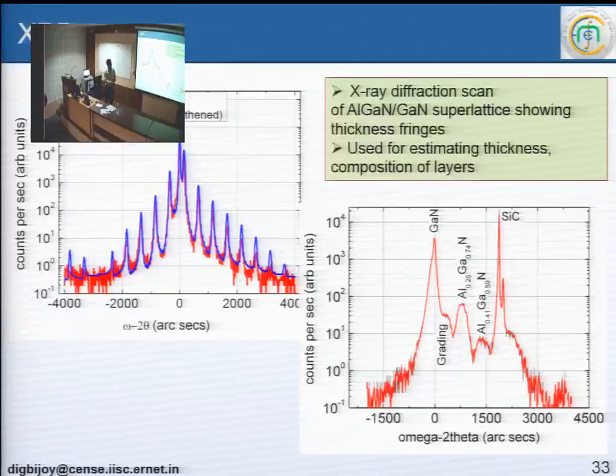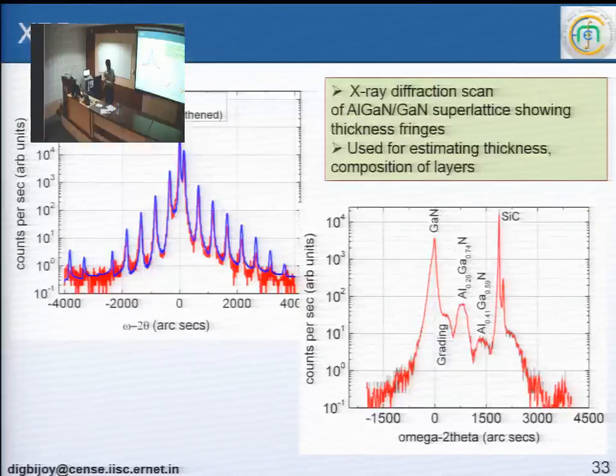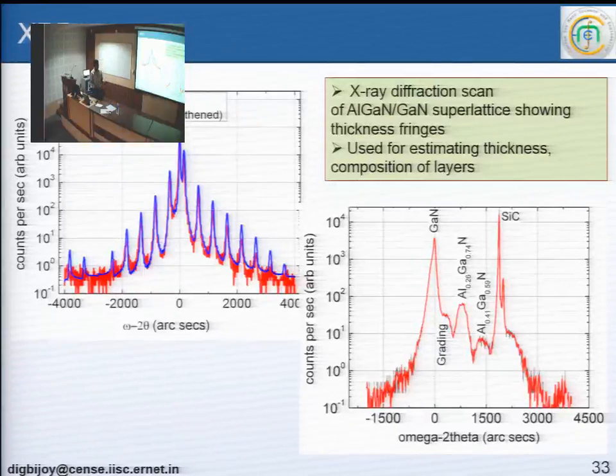And here I am showing you a scan, without the fitting, of just AlGaN, GaN, different kinds of layers. It's not a superlattice, it's actually a transistor wafer. These different peak positions that you see correspond to different layers. The spacing between the peak positions will tell you the strain state, the composition of the layers, etc. So this is a very powerful technique that is used to understand the crystal quality and the composition of the layers, and this is routinely done for all transistor wafers that are grown.